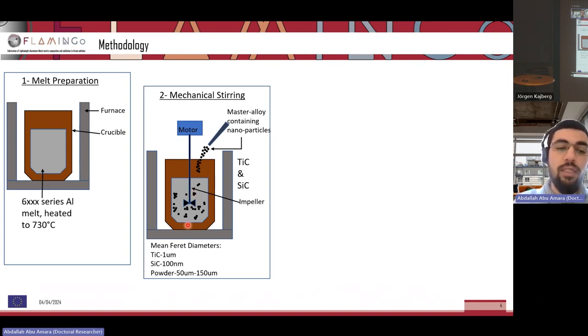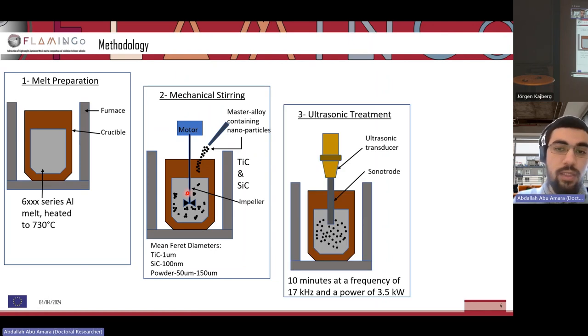So the titanium carbide particles have a mean diameter of 1 micrometer, and the silicon carbide particles have a mean diameter of 100 nanometers. So you can see the silicon carbide particles are a lot smaller, meaning sometimes we have to apply different stirring times. So we stir them for different periods of time in order to get all of the powder in. The third step is typically the ultrasonic treatment.